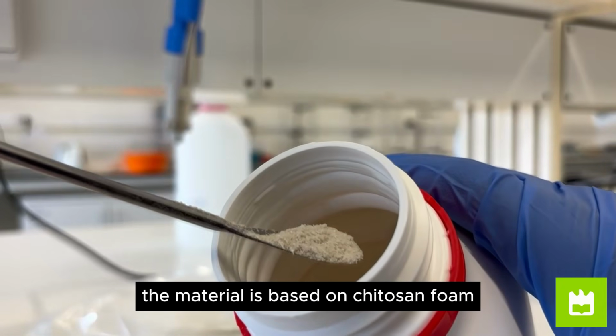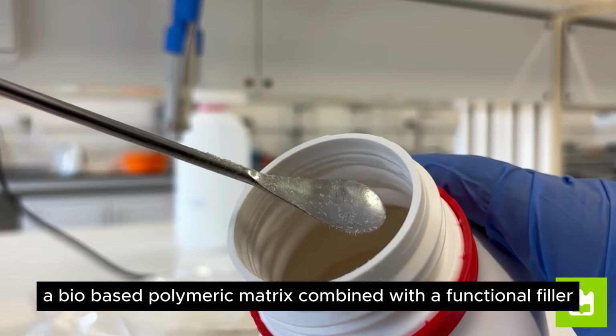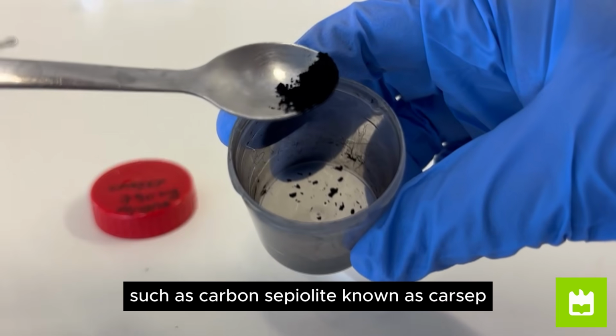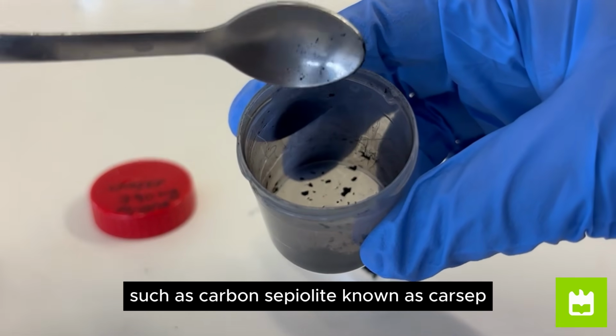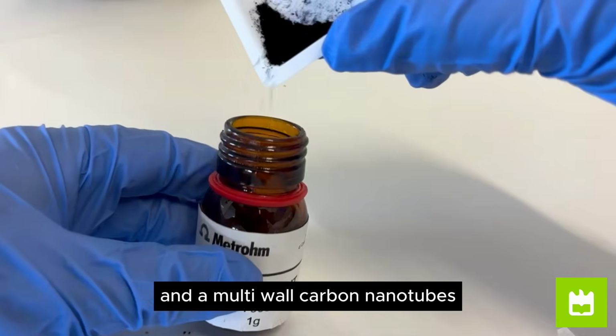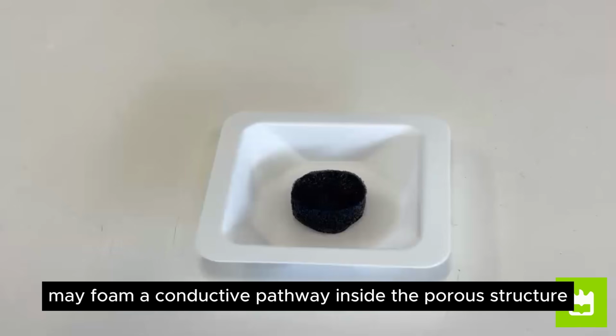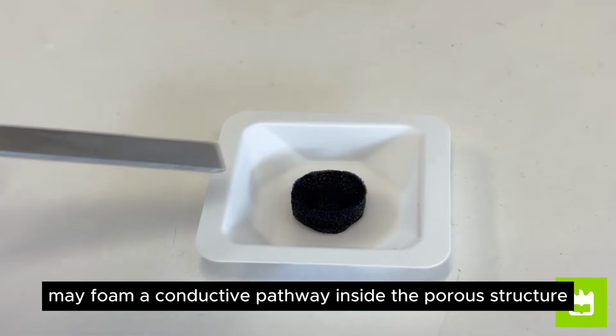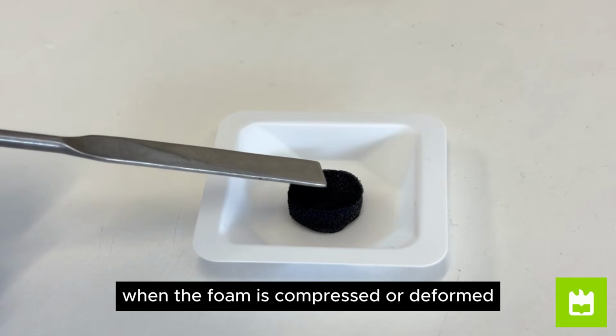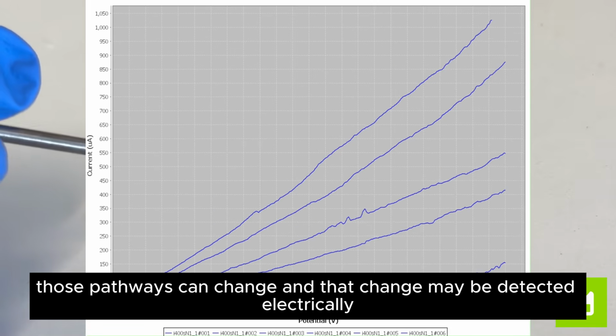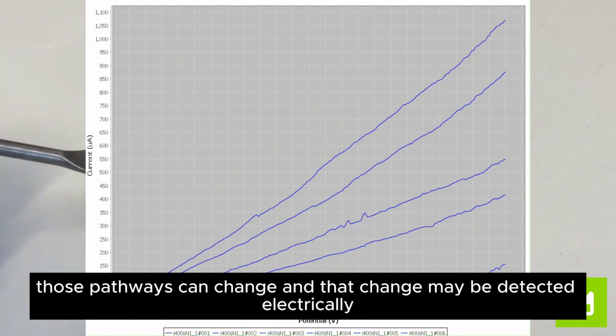The material is based on chitosan foam, a bio-based polymeric matrix, combined with a functional filler such as carbon sepiolite, known as CARSEP, and multi-wall carbon nanotubes. The idea is that these fillers may form a conductive pathway inside the porous structure. When the foam is compressed or deformed, those pathways can change, and that change may be detected electrically.